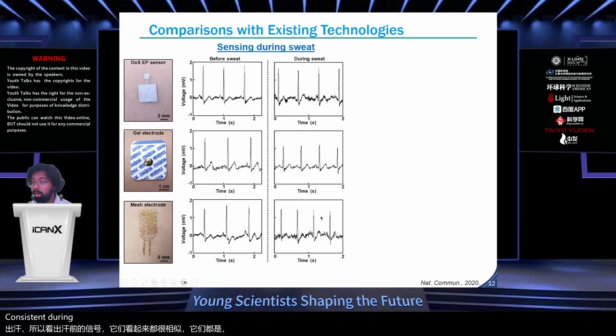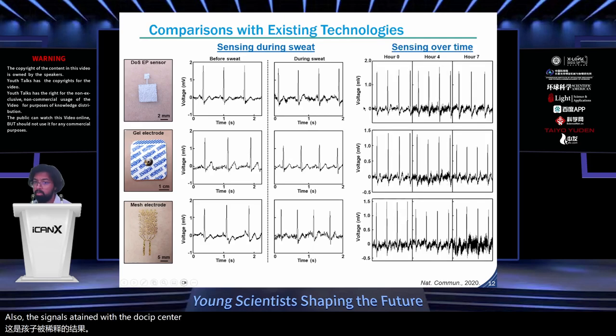During sweating, the signals for the drawn-on-skin and mesh electrodes remained consistent. But for the gel electrodes, the signal clearly degraded, because of the diluted gel electrolyte. Also, the signals attained with the DOS-EP sensors were relatively consistent over a 7-hour period.